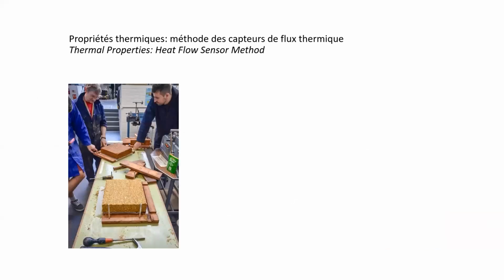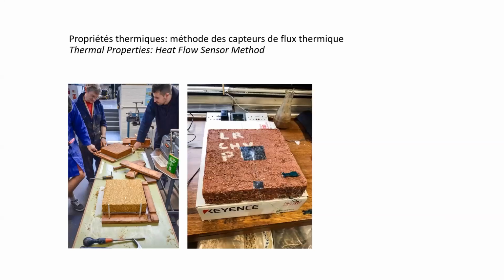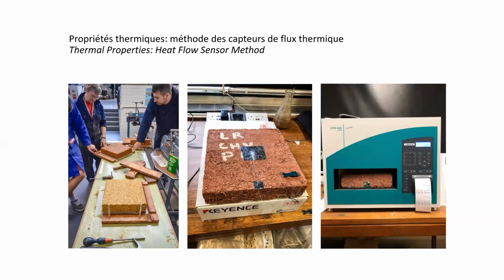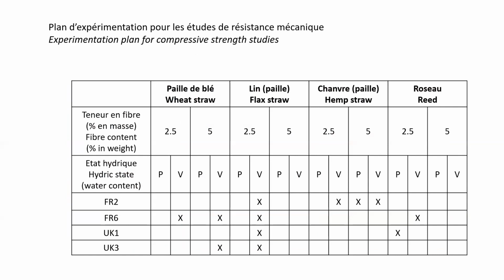So we then, from there, decided to work on implementing different tests, different preparations of samples, especially for the thermal layer. We created these blocks, and then we put these through different testing machines to determine their thermal resistance using heat flow sensors that you can see in the pictures here. So different mixes were then tested using these methods.